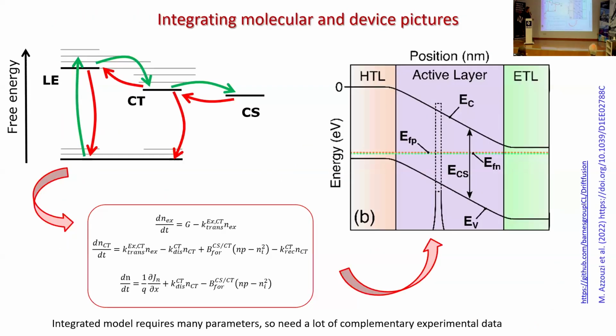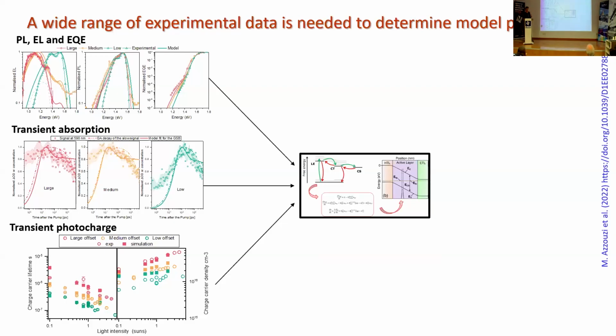And so to do that, we needed to consider not only these recombination rates, but also the whole process of photocurrent generation. We did that by making a device model in which this physical chemistry part is embedded into the equations, so that at the same time we could think about what we generate from our semiconductor device and what parameters control these transitions at the interface, and what effect those parameters would have on the outcome. And when you have a model like that, you have very many parameters. And when you have very many parameters, it's very hard to find the unique set of parameters that would explain a single piece of information.